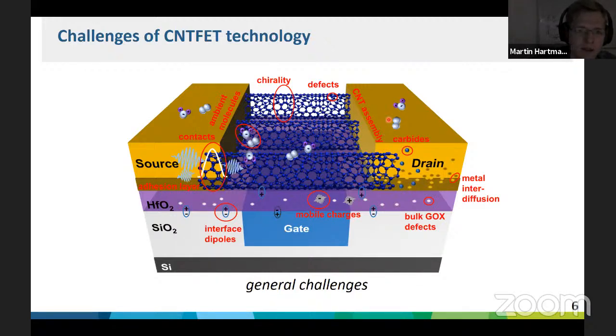Another important aspect is that you need to use CNTs with a low defect density, and your pre-treatments should also not increase the defect concentration on the CNTs too much. Then we want to use a certain chirality of the CNTs. That means a certain crystalline structure of the CNTs where we only have semiconducting and no metallic CNTs. And then another important aspect is the assembly. How are the CNTs assembled or arranged? Because we want to bridge the source and the drain by the shortest possible distance, and we want to reduce the interaction between the CNTs.